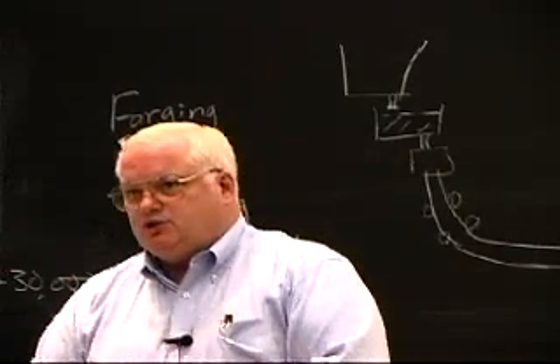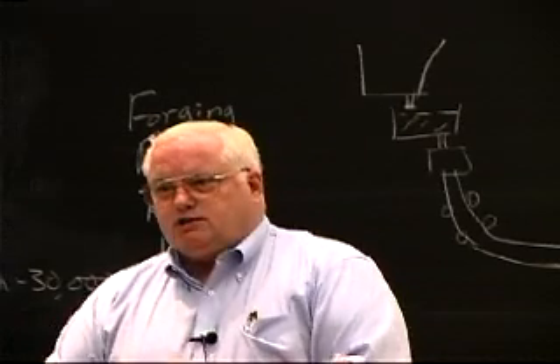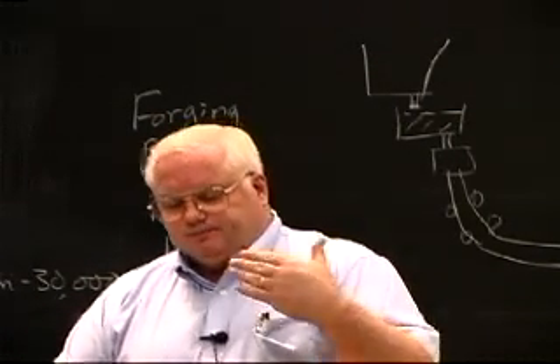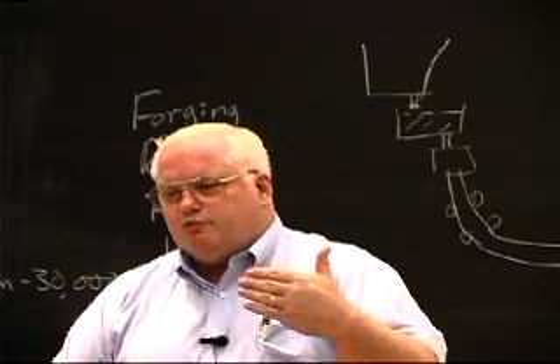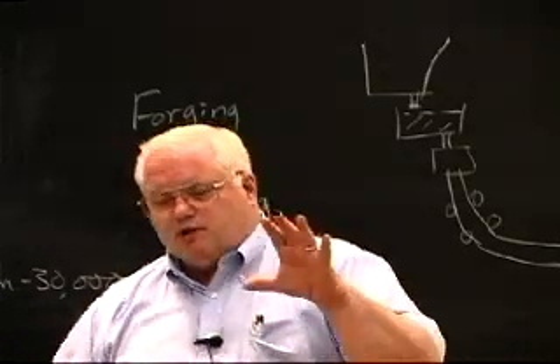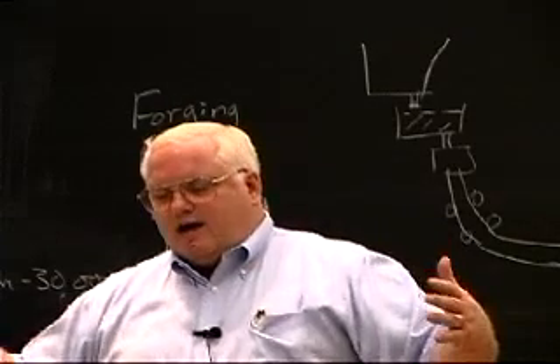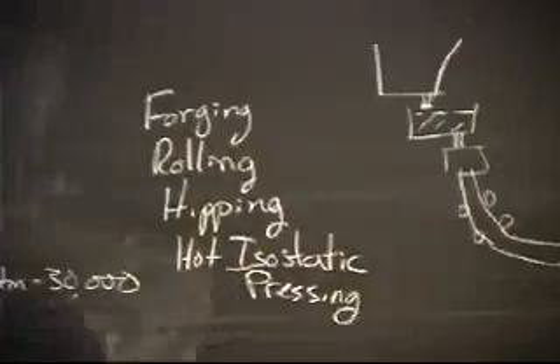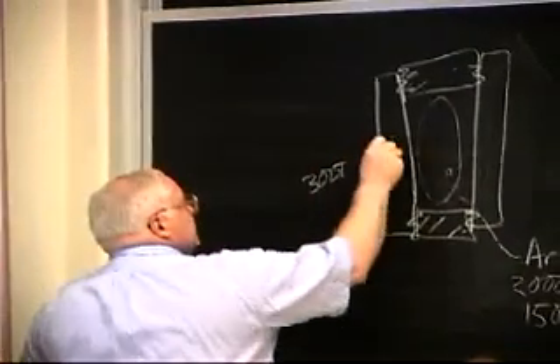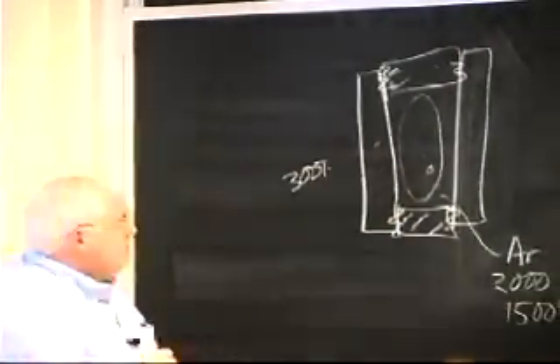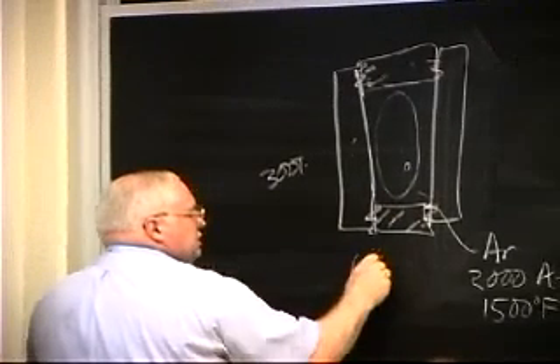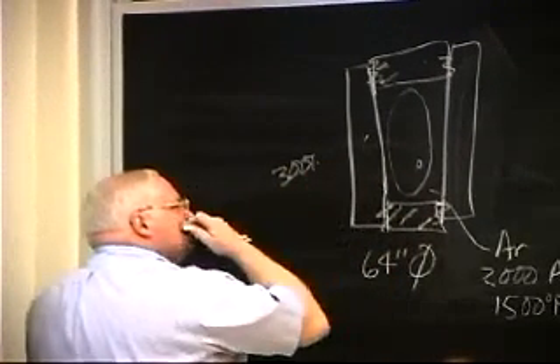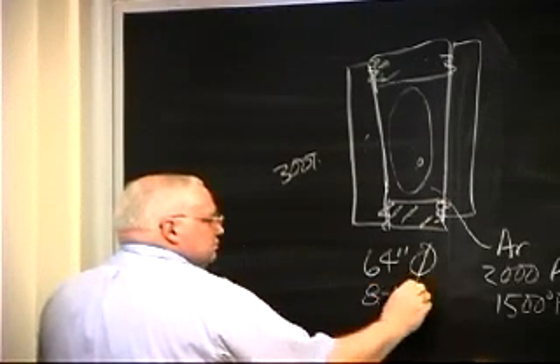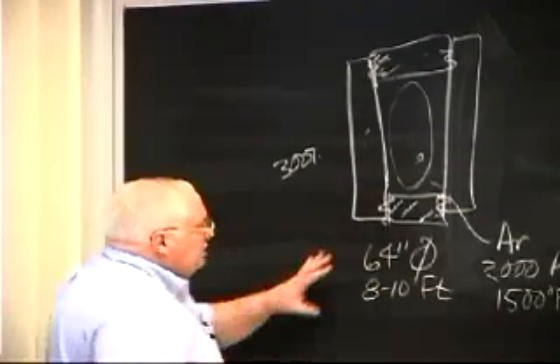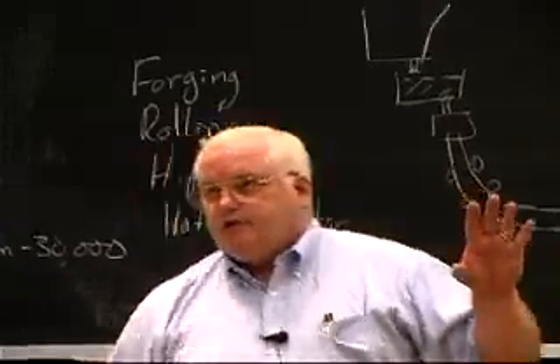You go up here to North Andover, Massachusetts, where they have one of the world's largest hipping presses at a company called IMT. The predecessor of IMT 30 years ago was actually a spin-off from some of the people here at MIT, but basically they have a press where the chamber weighs about 300 tons. Okay, it's about 200 tons for this and about 50 tons for each of the end caps. And the chamber is 64 inches in diameter. And the height is, I don't remember, about 8 or 10 feet tall. Okay. A typical cycle in this thing takes 24 hours. And one of these, about 3 or 4 years ago, blew up.